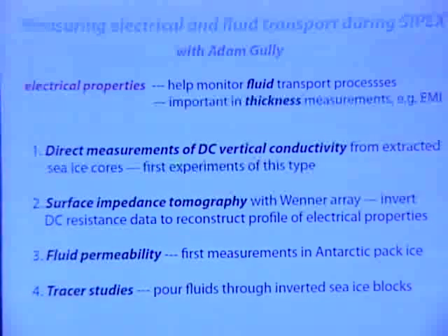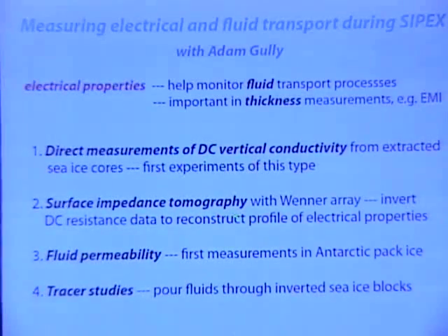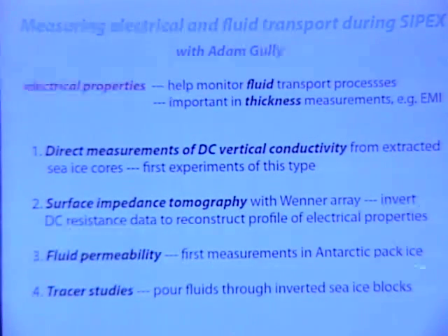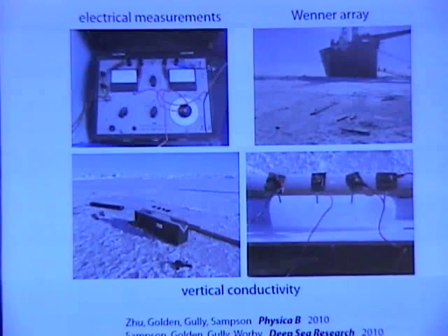We made direct measurements, the first direct measurements of DC vertical conductivity from extracted ice cores. We did surface impedance tomography, like putting electrodes on your chest to tell what's going on inside. We actually made the first measurements of fluid permeability in the Antarctic ice pack, and we did tracer studies where we poured fluids through inverted ice blocks. This is some of our 1960s era electrical boxes, and here's our extracted cores doing electrical measurements with the aurora in the background.